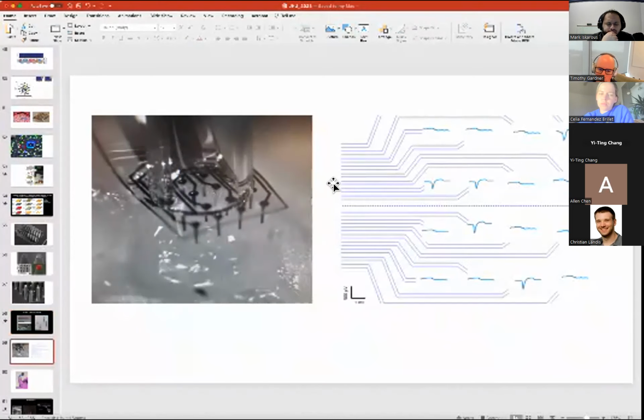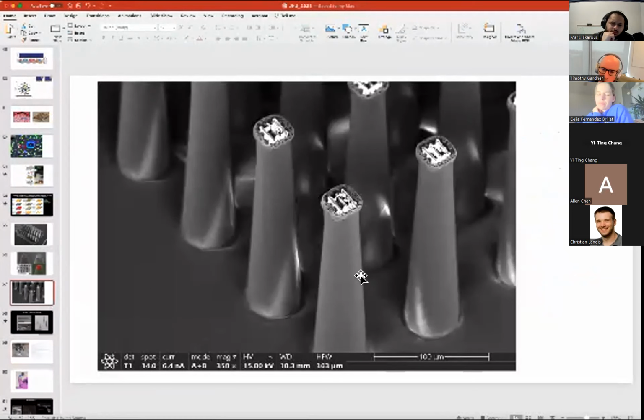But just kind of initial insertions, this is what that array looks like. A bed of nails, similar to the Utah array, but now on a really flexible substrate with protrusions that potentially are quite sharp and thin. And current work in the lab is seeking to replace that parylene insulation with silicon carbide.